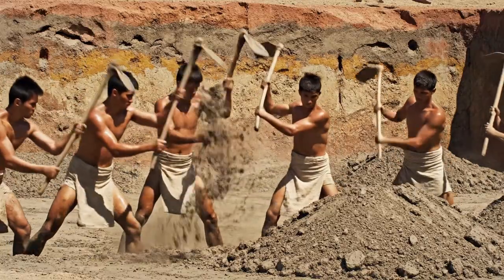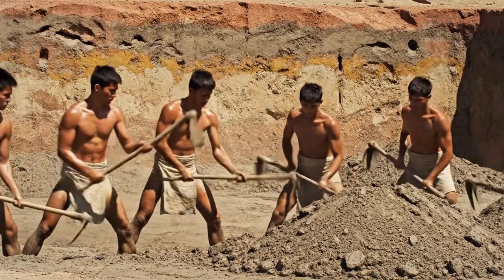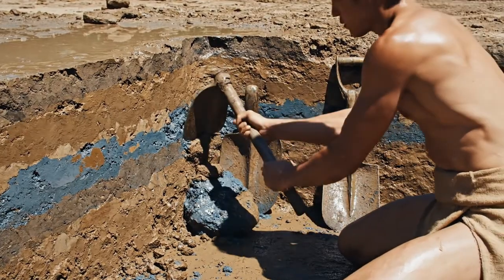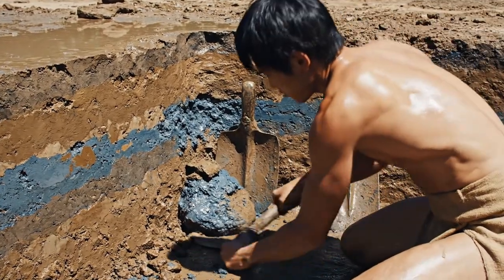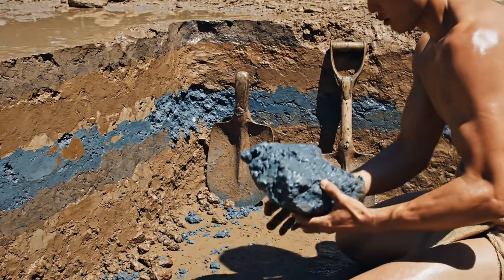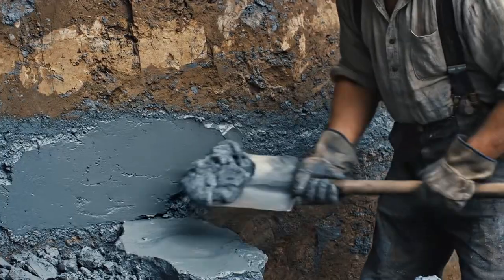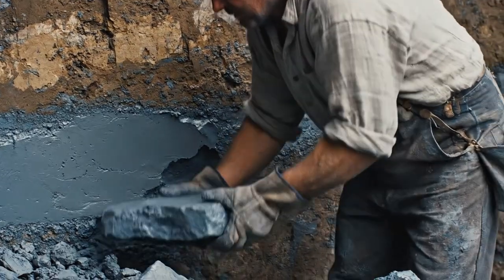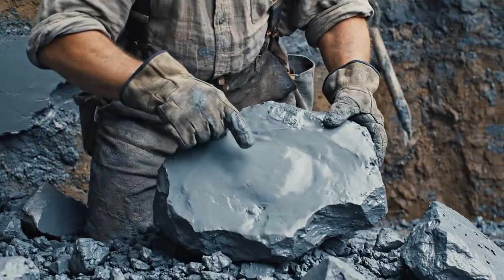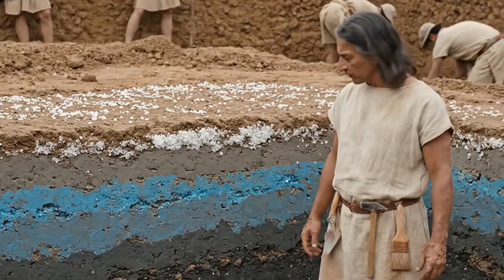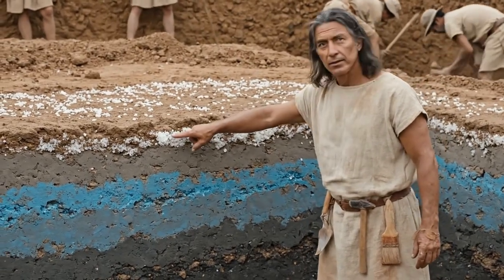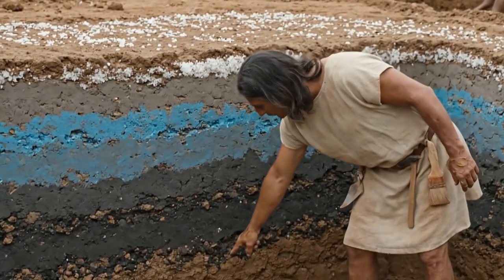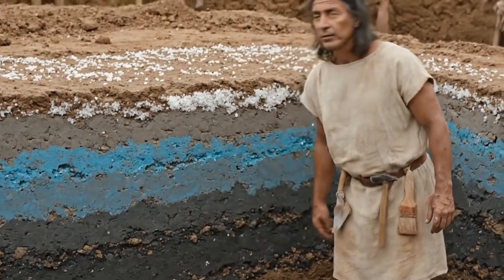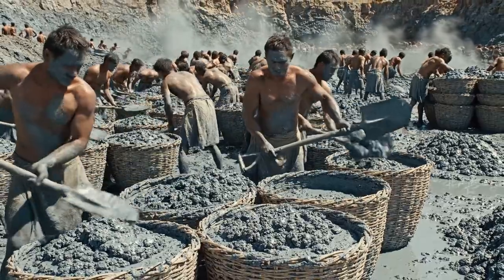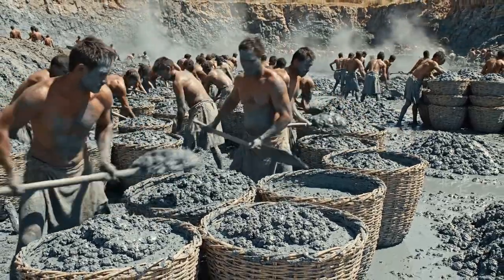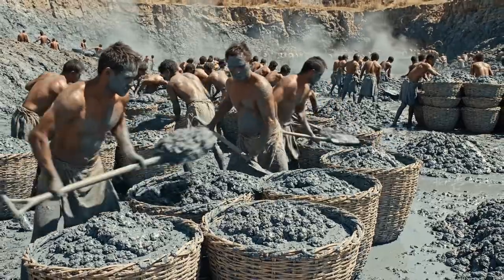The diggers are working in teams of 4, using bronze-bladed tools that look like wide hoes, cutting into clay deposits that were underwater just months ago during the spring floods, and they're digging down about 3 feet to a layer of blue-gray clay that experienced brickmakers know makes the strongest bricks, avoiding the top layer that's contaminated with salt crystals left behind by evaporating water, and avoiding the deeper layers that contain too much organic matter that will rot inside the brick and create weak spots.